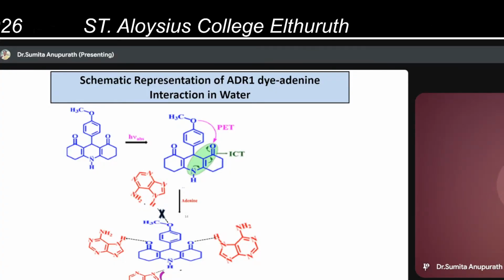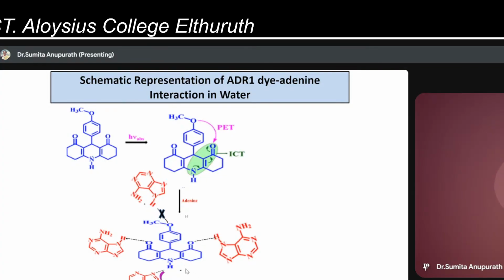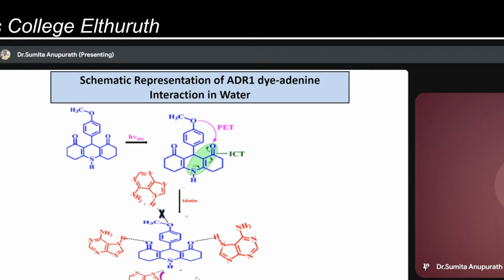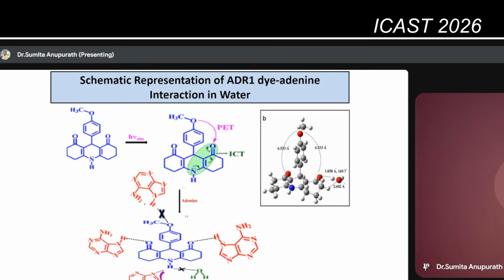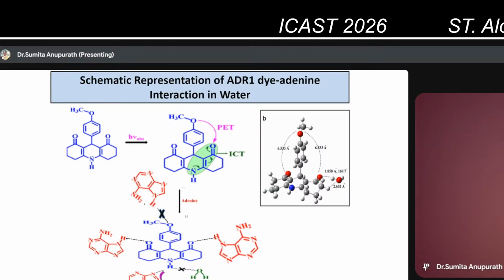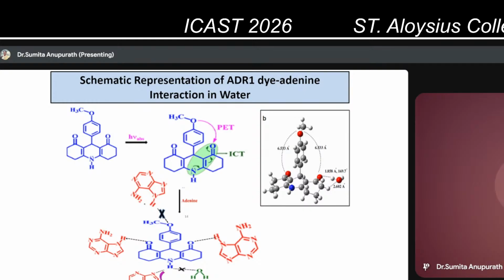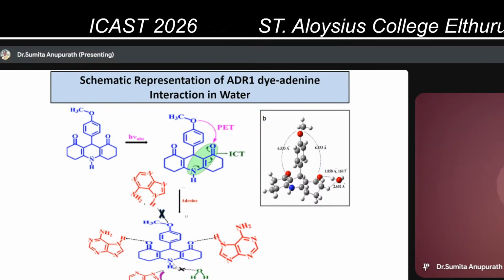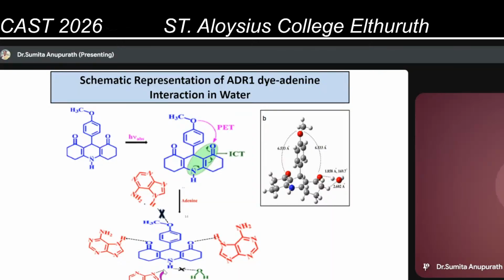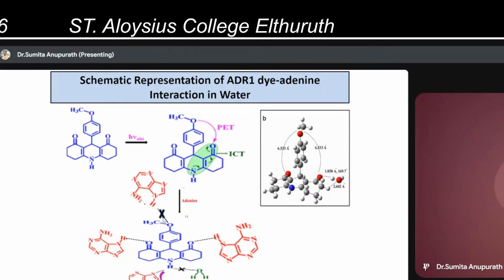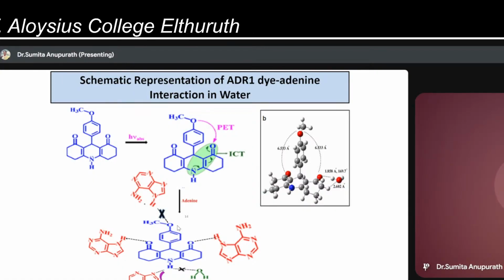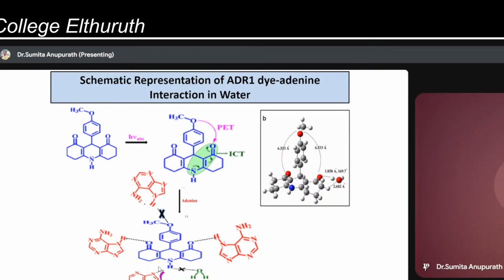At the same time, the system has water also. So there is a possibility for water also to bind through hydrogen bonding. But again, the same quantum mechanical studies show that water does not prefer to bind here, and rather it prefers to bind with the carbonyl oxygen. Now, why does this happen? This is because when adenine binds to the NH group, it forms a more stable complex than when it binds with the methoxy oxygen. So based on these energy stabilization studies, we were able to understand that adenine prefers to bind either at the carbonyl oxygen or at the NH position.